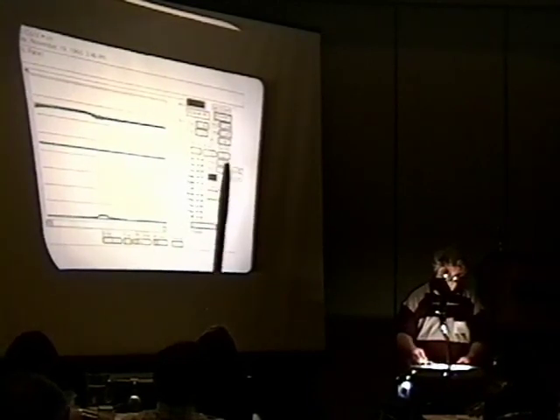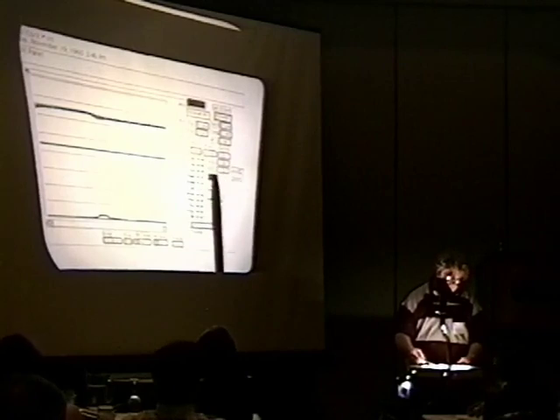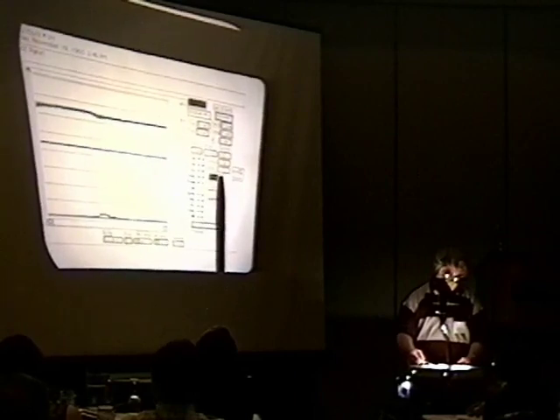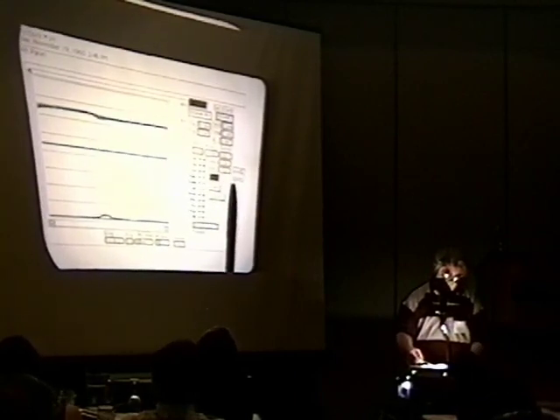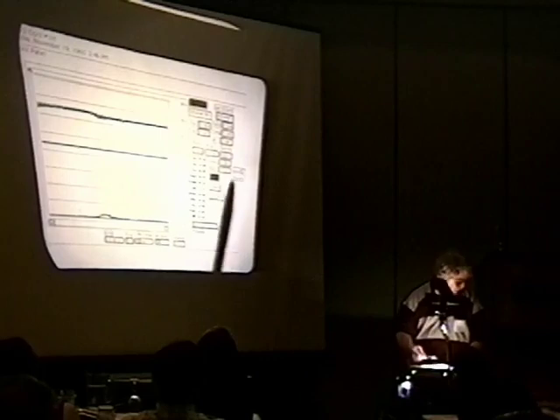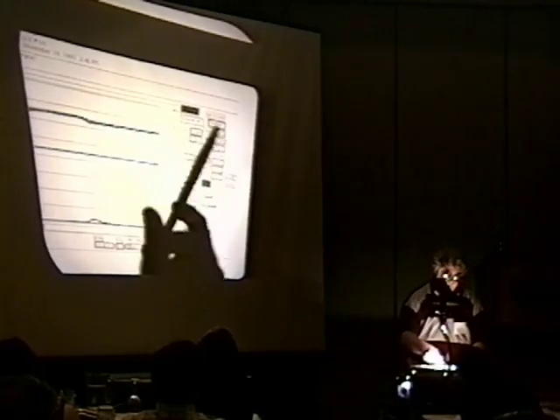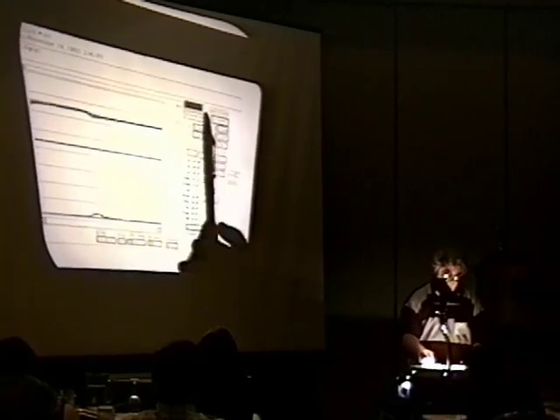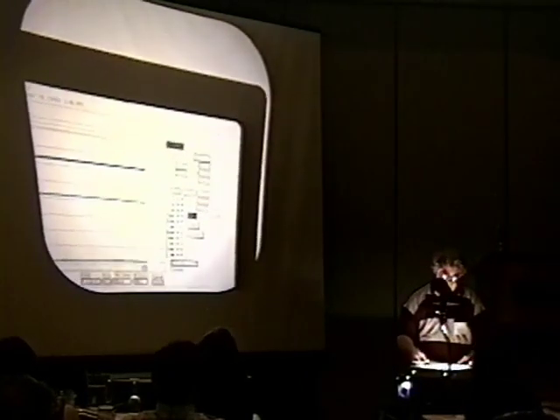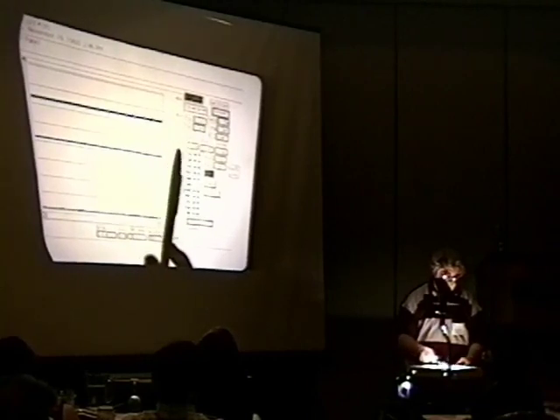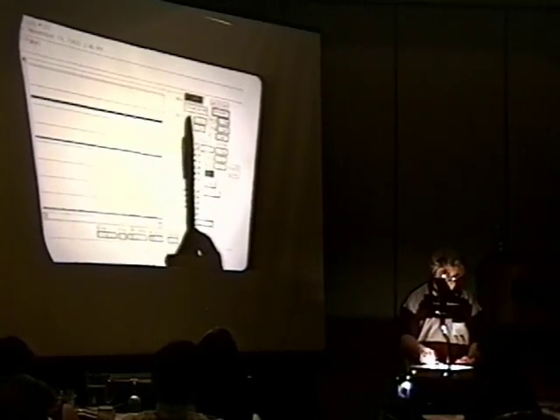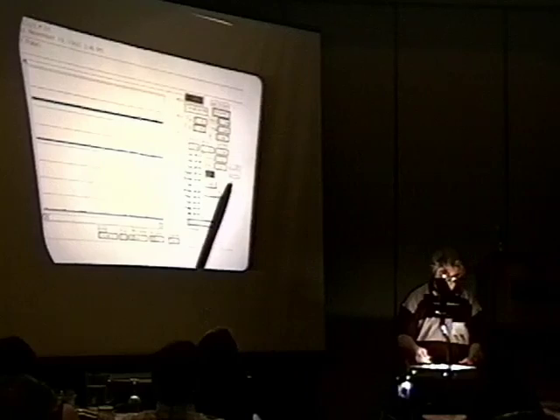And you can see that the input power, see where's the input power here, is about 0.02 watts. The excess power was about 0.12 watt for about a 550% gain. Okay, this was, by the way, I should add, cell number 72. It was a cesium cell. And I'll explain what this X is in a minute. Okay. Here again is that same cell, looking at it almost 11 o'clock later in the evening, and still about a 500% gain.